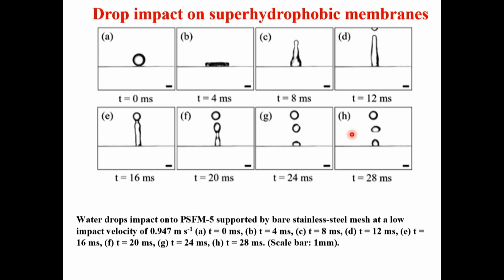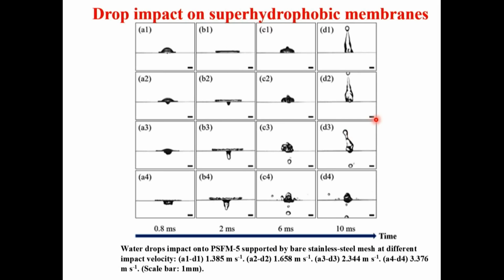Okay, very good. But the problem here is that the velocity of impact is only 1 meter per second, and it's interesting to go higher. So let's take a look at what happens when you go higher. These are a series of experiments where velocity is increasing. I'm not going very high, essentially 2.3 meters per second. In this case, you already see quite a lot of penetration of water through this superhydrophobic membrane. Okay, so it appears that superhydrophobicity is a miracle, not even a miracle, but a mirage. You see that the water easily goes through the Teflon membrane, with additional roughness, and you cannot stop it when velocity is increased to 2.3 meters per second.